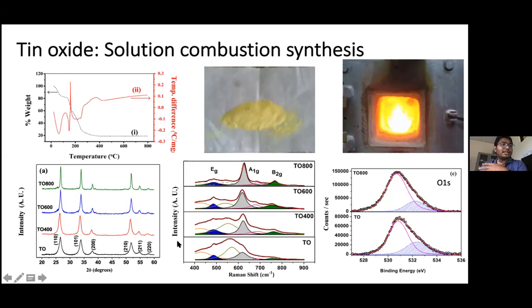As you can see in the XRD and the Raman particularly, the Raman of the as prepared sample, which was basically quenched from high temperature, showed a very large defect related Raman mode, which was not supposed to be present in a regular crystal of SnO2. This is not allowed by the symmetry and Raman active modes of SnO2.